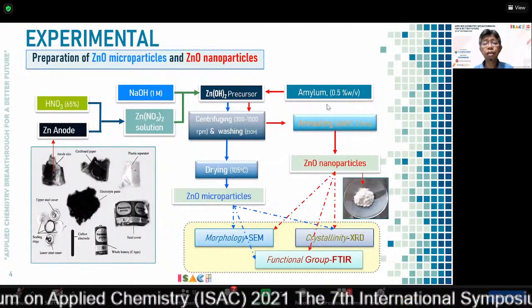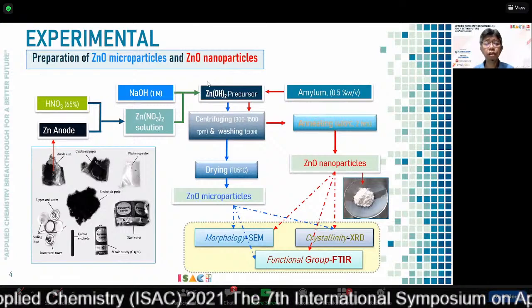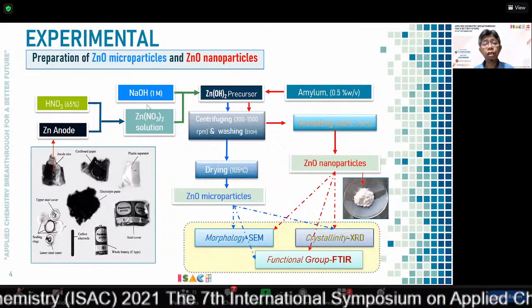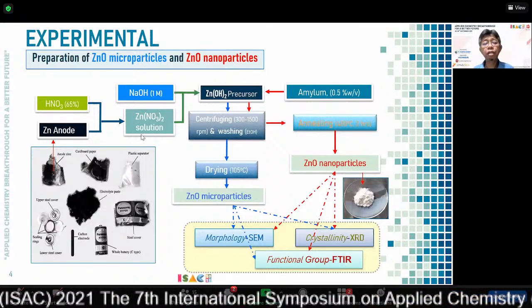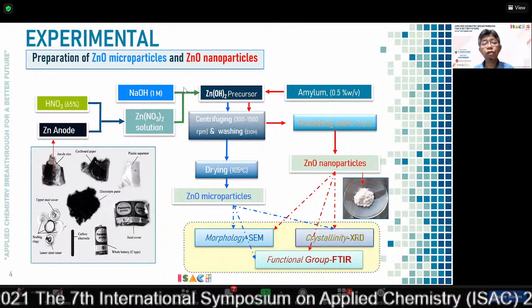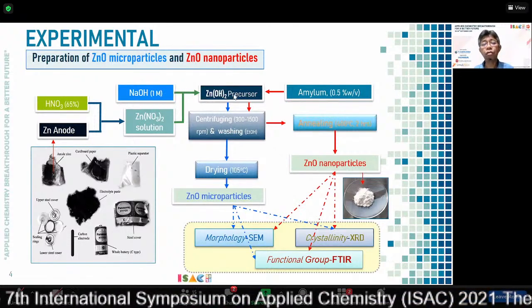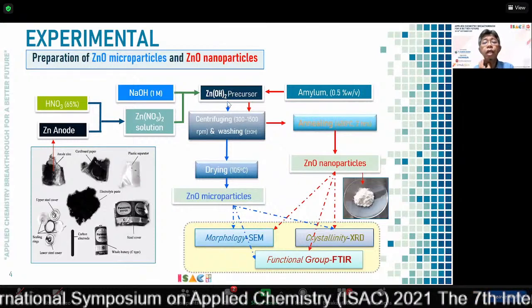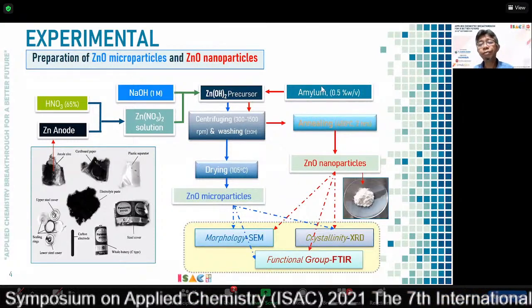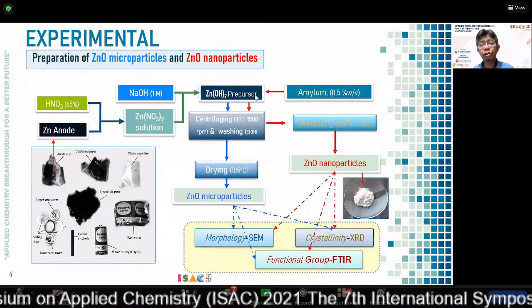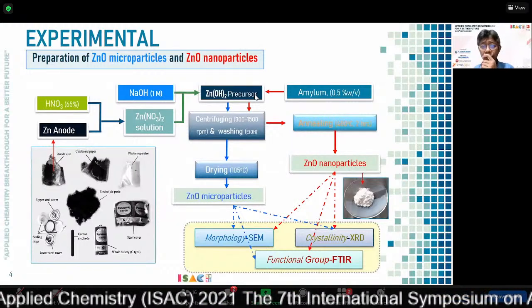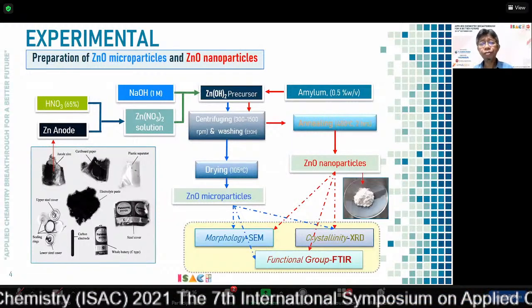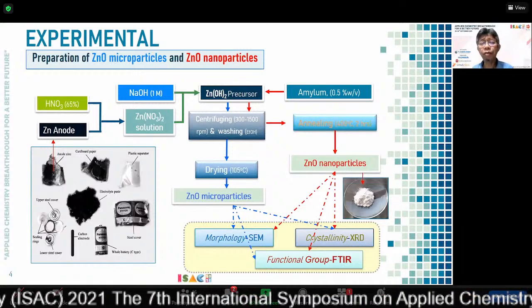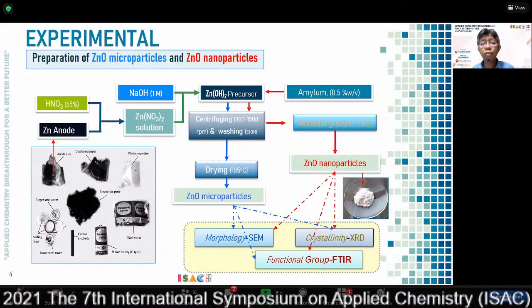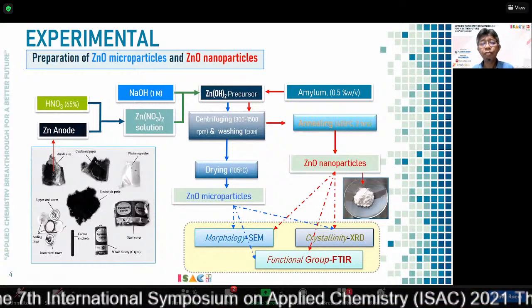On the other hand, for the zinc oxide nanoparticles, once we obtain zinc nitrate, and we neutralize with sodium hydroxide in order to have the precursor zinc hydroxide, we also add amylum as a capping agent to control the pore size, the particle size and structural shape. Once we mix, and then we separate it.